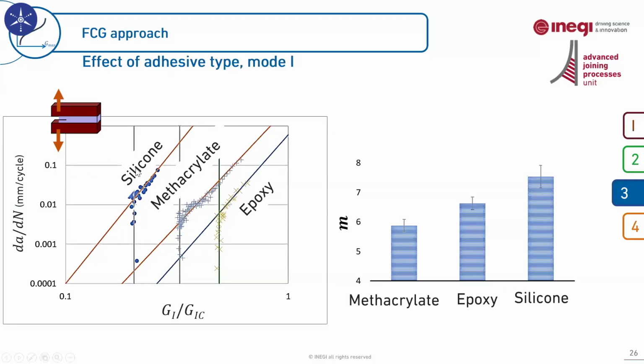And I need to highlight this point that these adhesives are really different adhesives in terms of strength, elongation, even fracture energy in quasi-static loading condition. But when we tested them under cyclic loading, we see more or less similar slope in Paris law curves. And in this bar graph, you see that actually the slope changes from 6 to a bit more than 7. So that huge difference that we observe in quasi-static loading conditions and strength of these adhesives and elongation of this adhesive is actually not observed in M values under cyclic loading.